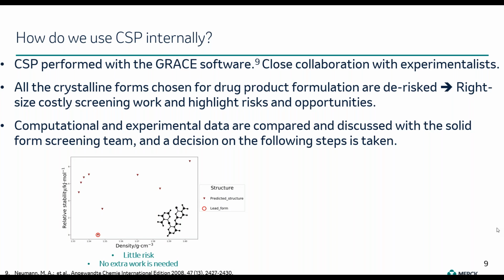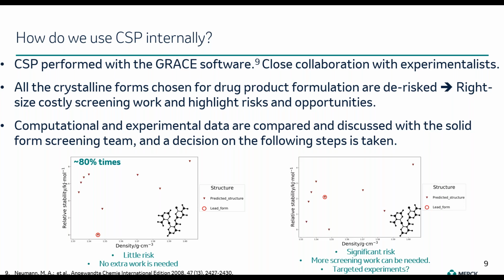So in this diagram, you see that the lead form, the form that has been developed for this molecule, is the global minimum, and is the most stable thermodynamically by quite a large margin. In this case, the assessment would be that there is little risk to the form being developed and no extra screening work is needed. And we see this happening in our cases approximately 80% of the times, which is very good in the sense that this bodes very well for our experimental colleagues, and this is the ideal case scenario. This is the scenario that you want to be in.